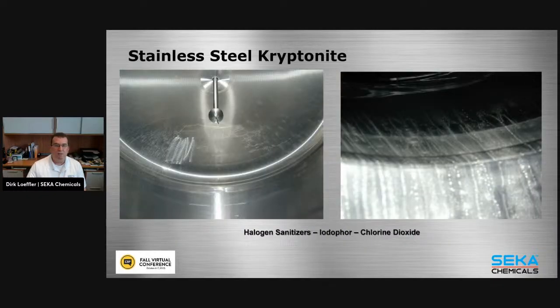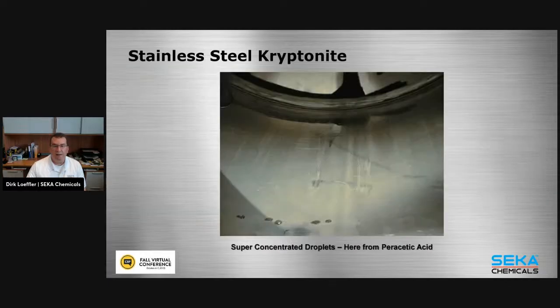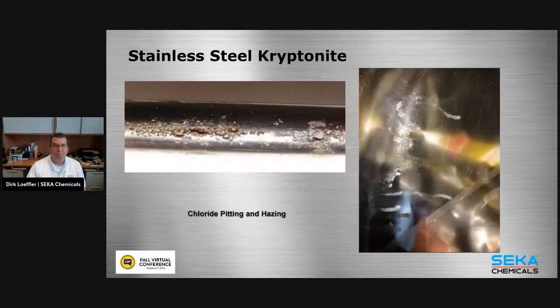Again, more pictures: chlorine dioxide, iodophor again. Got a million of them. Another interesting phenomenon that we're going to talk about later is called super concentrated droplets. This, for example, was caused by peracetic acid. We get into this a little bit later. Chloride pitting: if you apply chlorinated foam cleaners, for example, on the exterior of pipes and forget to rinse it, you end up with something like this.